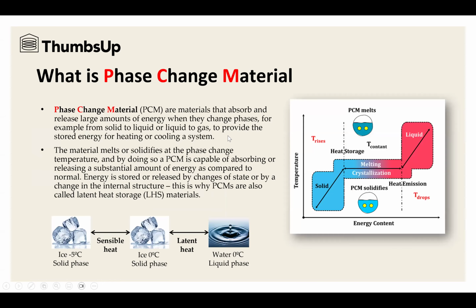So what is a phase change material? It is a material that can absorb or release latent heat when it changes phase. For example, ice at 0 degrees is in the solid phase. But if it absorbs latent heat, it can change to water, also at 0 degrees. This latent heat is around 300 kilojoules per kilogram, so it is a lot of energy we can use. Also during the phase change, the temperature is quite stable at this stage here. That's why we think the phase change material is a very good material for thermal energy storage.